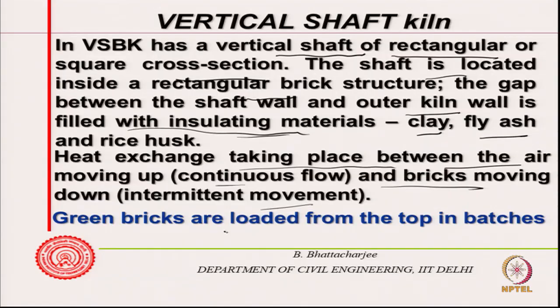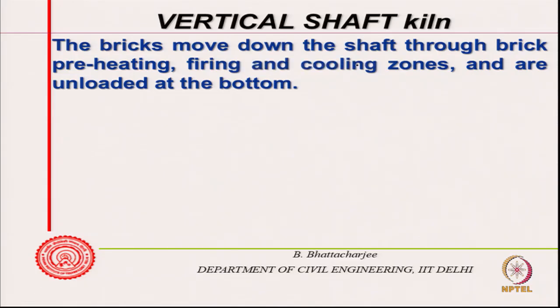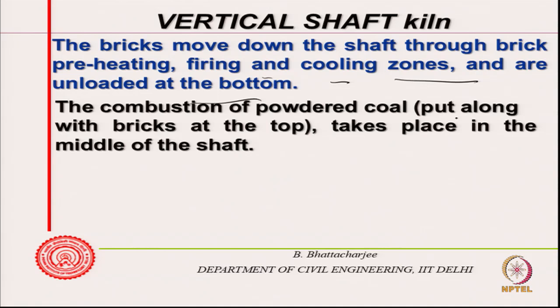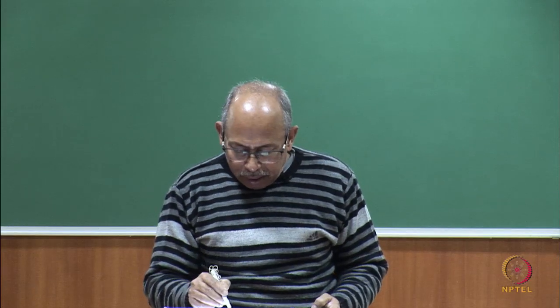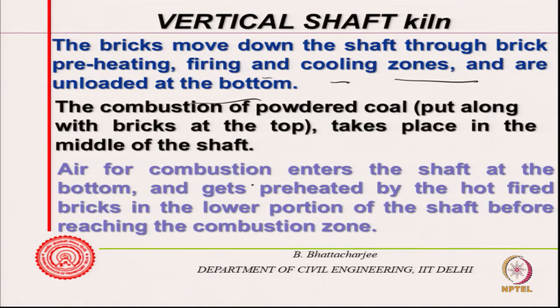So, let us see some diagram. Green bricks are loaded from the top in batches. Bricks move down the shaft through brick preheating, firing and cooling zones and are unloaded at the bottom. Now, the combustion of powdered coal put along with the bricks at the top, right. As the hot gases go up, they will actually ignite the coal themselves, and firing will occur simultaneously as the intermittent load goes downwards. So, it takes place in the middle of the shaft. Air for combustion enters the shaft at the bottom and gets preheated by hot fired bricks in the lower portion of the shaft before reaching the combustion zone.